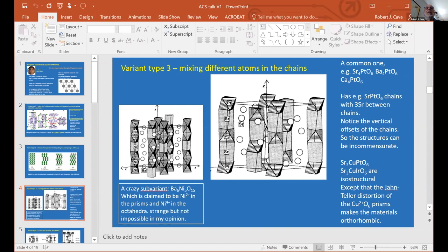Now, I think these are a testimony to how wonderful solid-state chemistry is as a field, because who could predict such a crazy thing that in the case of Sr4PtO6, it's a mixture of strontium that's in a cavity, like an A-site cavity, and strontium that's in a chain. It's a pretty hard thing to imagine that this happens. And then in some cases as well, I don't even know if my pointer is showing up, but basically the chains can be incommensurate. So a chain in the middle of the cell doesn't have to be lined up with a chain on the corners of the cell. So they can be particularly odd and entertaining.